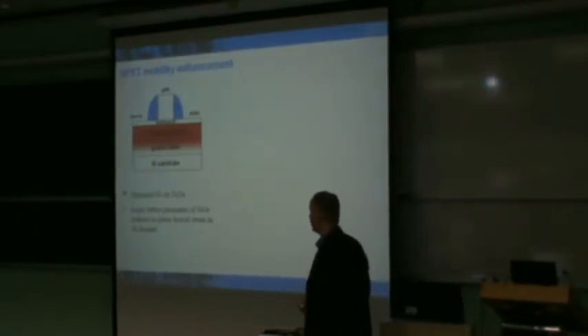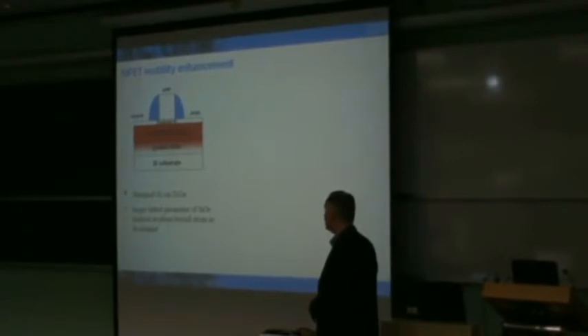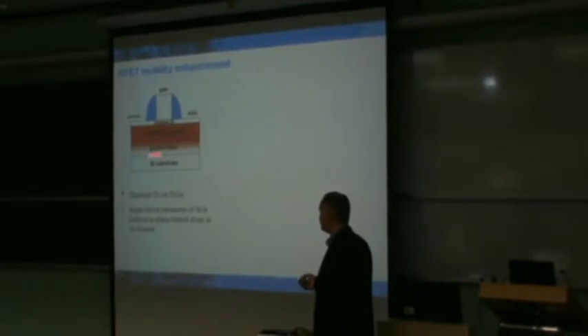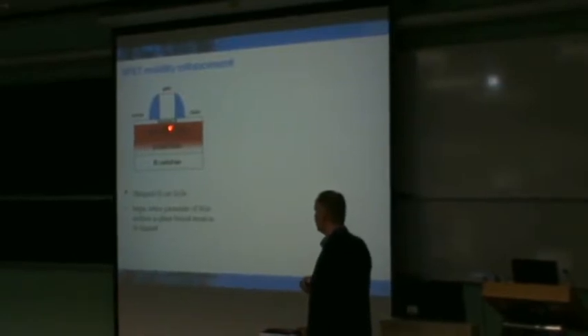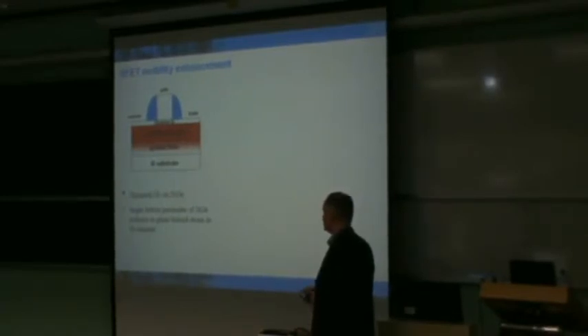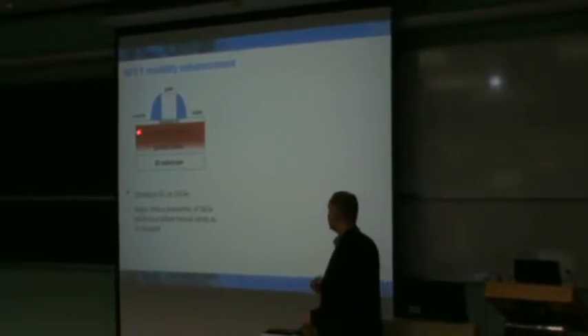Okay, so if we give a couple of brief examples about how this has been incorporated, when we look at N-type field effect transistors, the mobility enhancement that first was really the first platform in which this was used was to place silicon, and we call it strained silicon in this case, because it's grown heteroepitaxially on a buffer layer of silicon germanium. So this could have a certain fraction of germanium within your silicon. And the reason for doing this is that germanium has a larger equilibrium lattice parameter than that of silicon. And so you can extend the template on which this silicon can be grown.